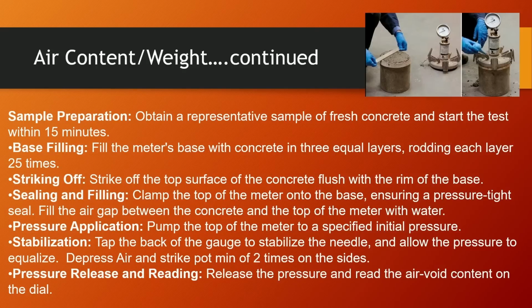Pressure application: you pump the top of the meter to the specified initial pressure. Stabilization: you're going to tap the back of the gauge to stabilize the needle and allow the pressure to equalize. You depress the air valve and strike the pot a minimum of 2 times on the sides. Pressure release and reading: you release the pressure and read the air void content on the dial.